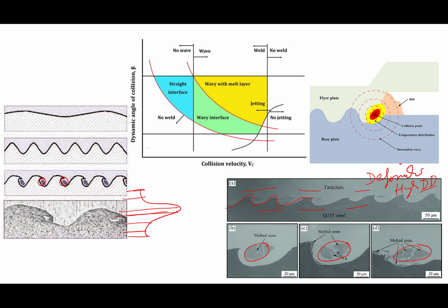But if the jetting results in partial melting and a lot of IMCs are formed at the interface, then this increase in hardness may be significantly high, which may correspond to, say, 200, and here it was 400, and here you may have 1000. So IMC formation may deteriorate the joint capabilities much more adversely. That is why melting has to be avoided in any case.